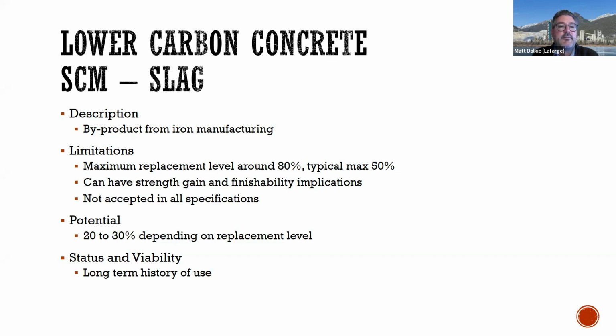So this has a maximum replacement level somewhere around 80%, but typically you would not use more than 50%, depending on your application. So it can be used at a higher level in comparison to fly ash. Again, can have strength gain and finishability implications and curing implications as well. Again, not necessarily accepted in all specifications.